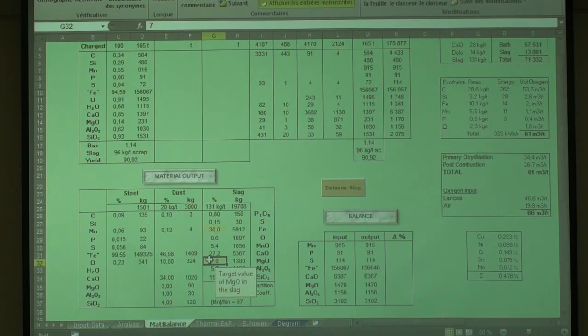Because for MgO I have two solutions. Either I don't put dolomite in the slag and I just rely on the refractory to saturate the slag with MgO, which is not very good practice, because then I have to repair the furnace nearly every 2 heats, and refractory material for repair costs money, repair time costs money and energy. So this is the first practice. You still have steel plants doing this.